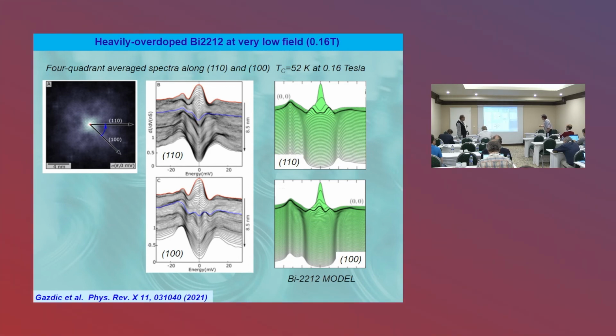Okay, maybe I should just summarize by showing you that most of the reports on spectroscopy of vortices in the cuprates and especially on BSCCO have been performed at very high fields, essentially above 2 Tesla or 1 Tesla. And it's only when we worked at very low fields that we recovered the zero bias anomaly predicted by the BCS framework. And also, it's the field intensity, so the vicinity of the other vortices, which trigger the occurrence of the conductance modulation we see in the cores of BSCCO.